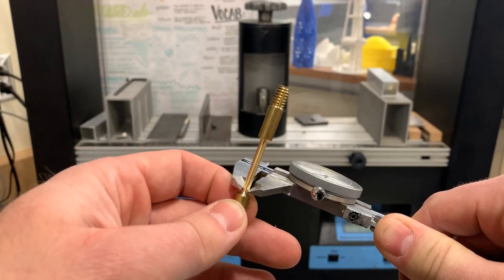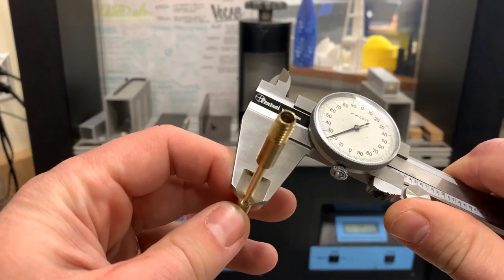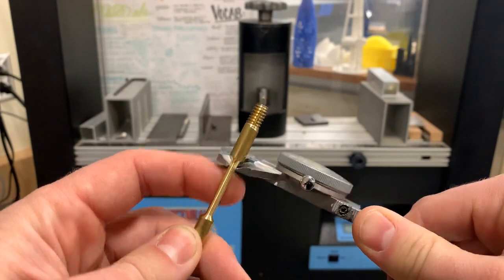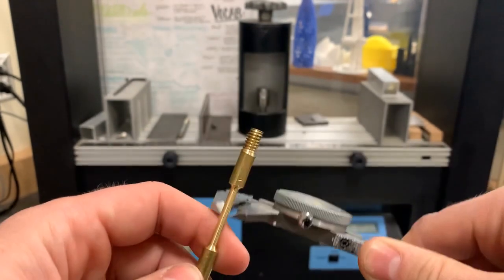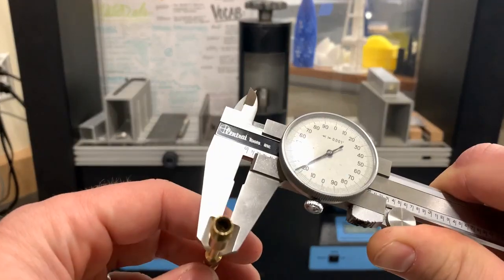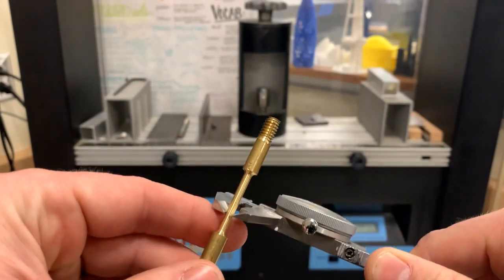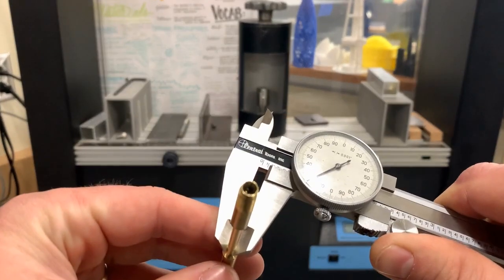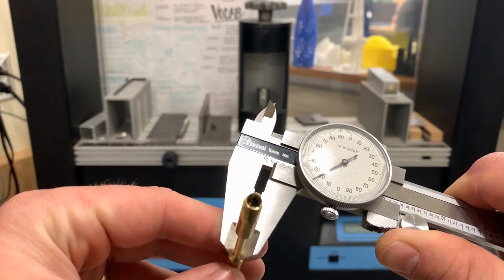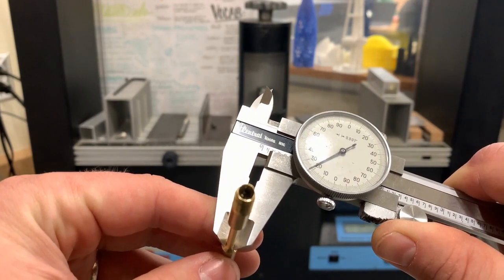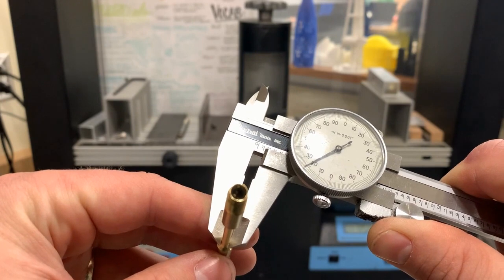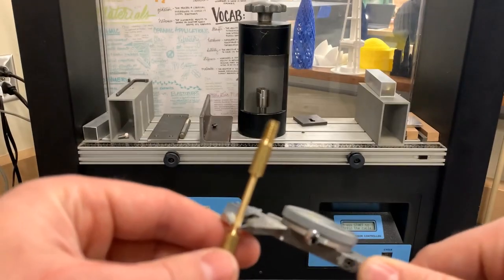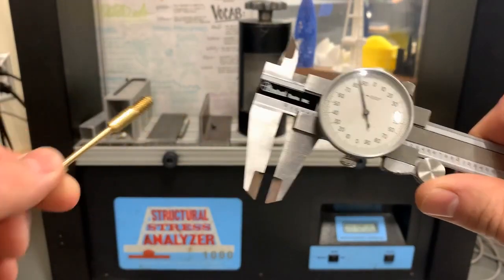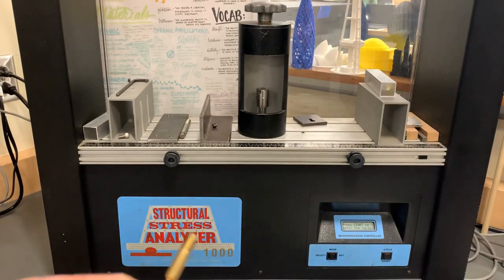It's a good idea to check at both ends as well as the middle, because there tends to be a little bit of variation from one end to the other. You want to find the point with the smallest diameter, because that's most likely where the sample is going to break. So this sample is measuring 0.121. That's the number I'm actually going to use in my math.